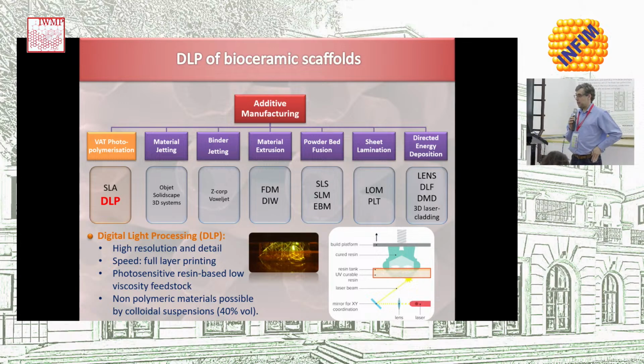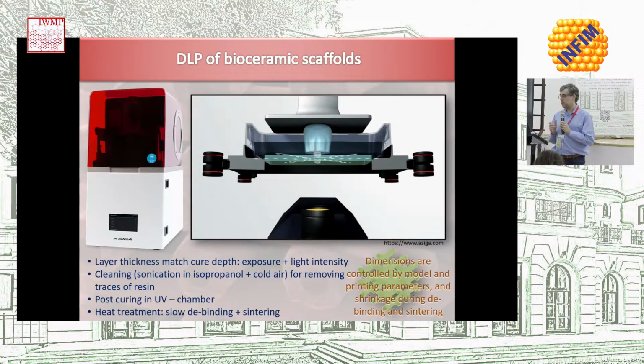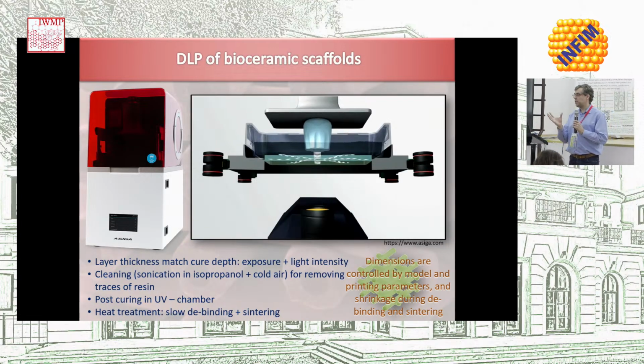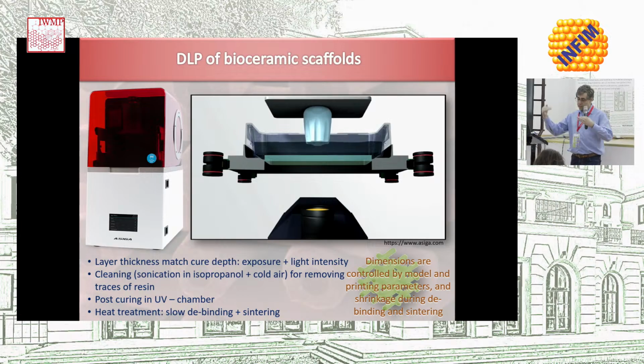Of course, you need to use photosensitive resin-based feedstock materials for that, usually very low viscosity resins. So in principle, it's a technique for polymers, but you can actually print anything as long as you can produce colloidal suspensions of those materials, powder from those materials, in these polymeric resins. The difficulty here is to keep the low viscosity that is needed for the printing process, because the printing process goes like this. You project the light and cure a single layer, then remove, put back your materials, and let the suspension go back below the sample. And for that, you need to have a very low viscosity suspension.